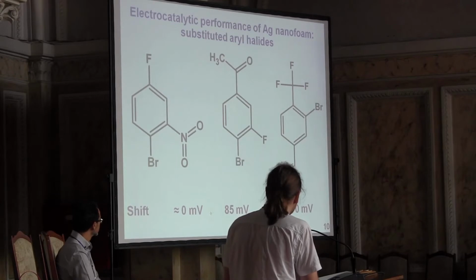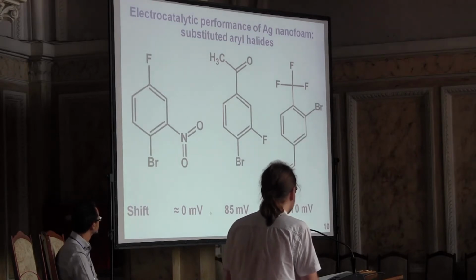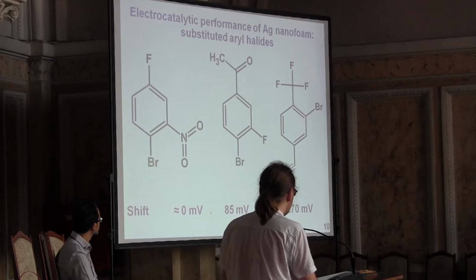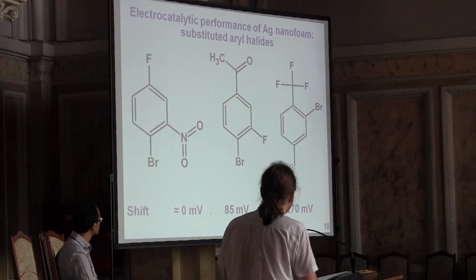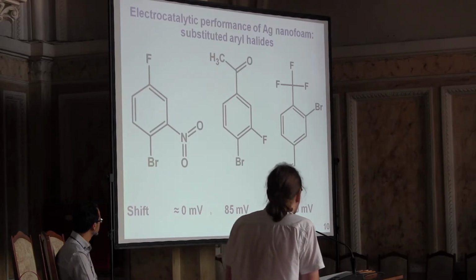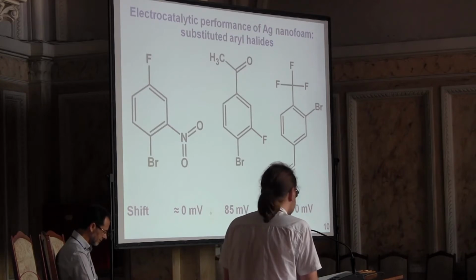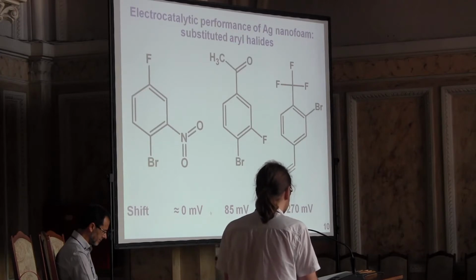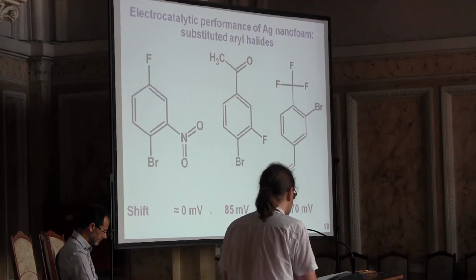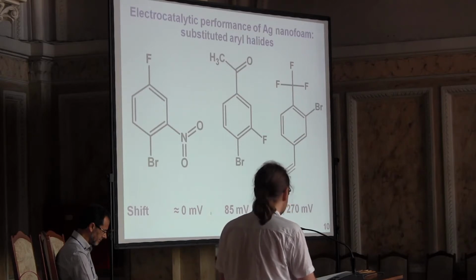The situation is a bit different in the case of substituted aryl halides. Contrary to the non-substituted benzyl bromide, for such compounds we can observe minor shifts of the potentials, or even no shift in the case of nitro derivative. In order to explain such difference and to find the exact description of the mechanism of reaction of these compounds, we need additional studies that will be a subject of further investigation.